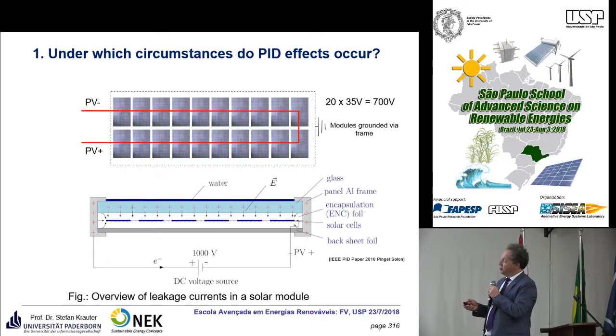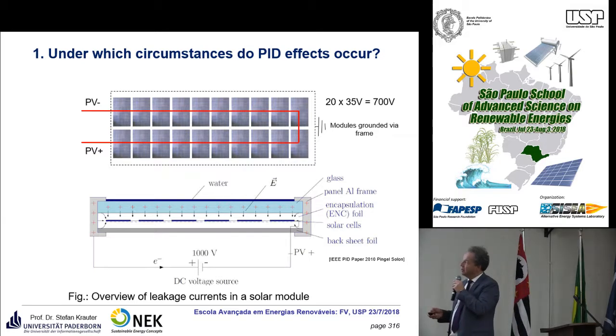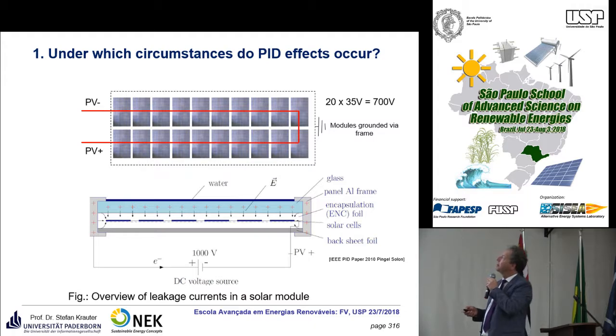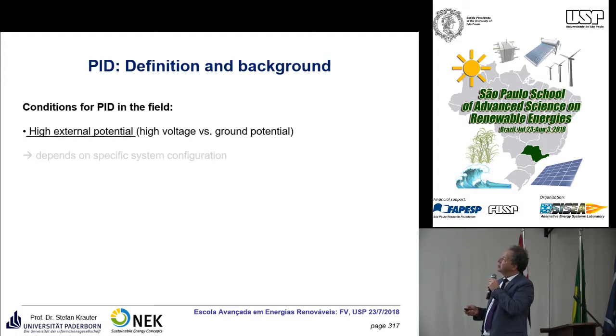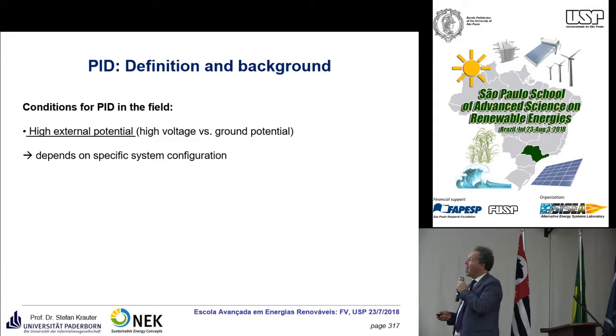So what happens? You have a negative and a positive pole, and depending on the leakage current, there is a movement of sodium ions from the glass or from the anti-reflection layer into the electrical field region of the solar cell. This weakens the electrical field in the solar cell and therefore reduces the power production of the solar cell. For this to happen you have to have a high voltage. Twenty years ago, nobody discovered it because the voltage was much lower.